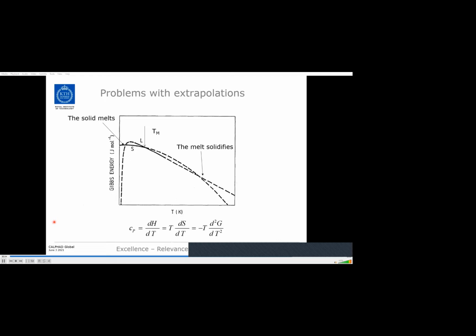When we extrapolate the Gibbs energies using the experimental heat capacities, Gibbs energy as a function of temperature will no longer be straight lines. They will be curved lines, which means that they may intersect. The Gibbs energy of the liquid and the Gibbs energy of the solid may intersect several times. So it is illustrated here where we have the normal melting point.